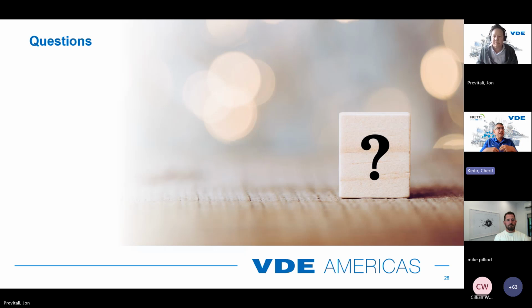One of the most common questions is, well, in the field you're more likely to get multiple impacts at the same time, right? Because you have a bunch of hail falling all at once. I think the critical point is the one Mike made earlier: impacting a module once or twice or 100 times is not going to weaken it. And this is the follow-up answer: that's because the failure is determined by the inherent flaws of the glass, and the compressive strength of the glass, which is the tempering. Hitting it with two shots at the same time, I don't think it will make a difference, because if anything, it will confuse the data. If we shoot it with 5 ice balls at the same time and it breaks, you're going to have to figure out which one broke it. So one at a time, I think, is fine.